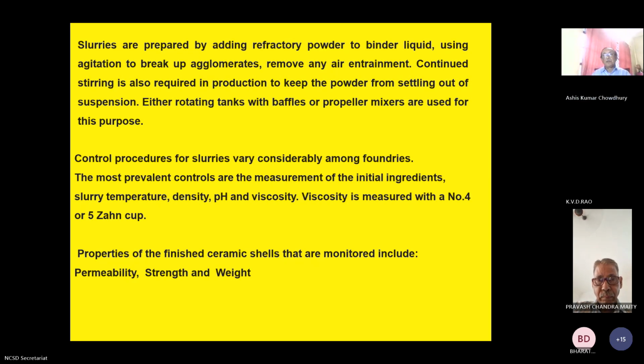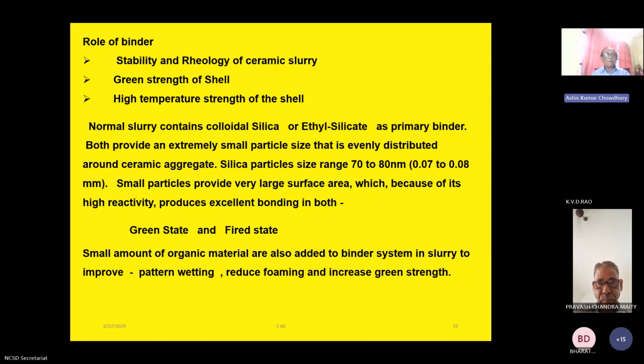Role of binder: stability and rheology of ceramic slurry, green strength of shell, high temperature strength of the shell. Normal slurry contains colloidal silica or ethyl silicate as a primary binder. Both provide an extremely small particle size that is evenly distributed around ceramic aggregates. Silica particle size ranges from 70 to 80 nanometer. This silica particle size of 70 to 80 nanometer is a very important thing for binding.